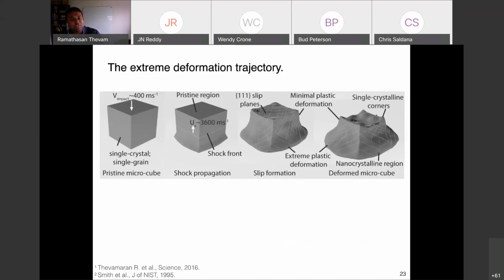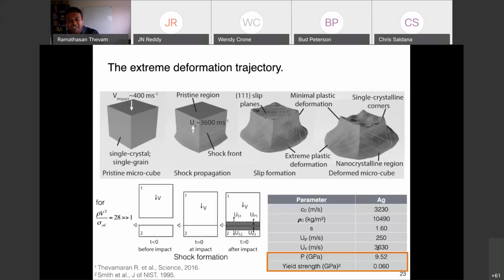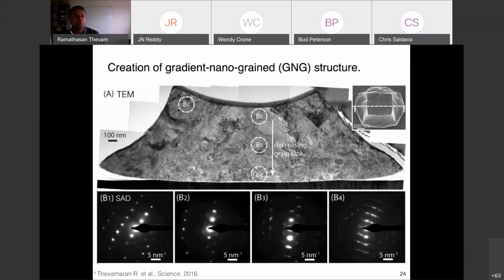What we think caused this deformation is that if you do a simple normal shock calculation, you will see that the pressure in the material goes all the way up to 10 gigapascal. The yield strength of silver is only 60 megapascal. So this is a huge stress. That will take the material into a hydrodynamic stress state in the bottom region, which shapes the material and causes its deformation. Meanwhile, the stress field interacts with the free surfaces to cause attenuation, so the top region deforms mostly by ordinary crystal plasticity. If you look in the TEM, you do see the characteristics of these two stress cascades at play. You see a more single crystalline region at the top, and it progressively becomes nanocrystalline at the bottom, as shown by the selected area diffraction.